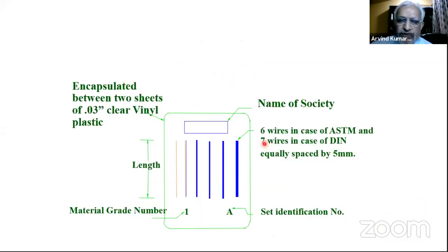Whereas in wire type, you have now ASTM wire type, you have 6 wires and there are 4 sets like this. Set A, set B, set C, and set D. And each set will have different range of thickness of wires. So for welds, we generally use these ASTM penetrameters to check the sensitivity of the film. The IQI is only used to check the quality of the radiograph, not the size of the defect.